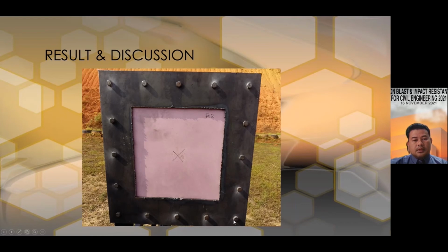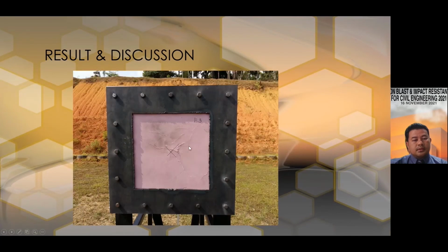Now, from observation, the gypsum board in case 2 does not have any damage at all. When there is no gap between the board and the steel plate, the board is good in resisting the compression force, but not the tension. The tension is provided by the steel structure. Compared to case 3, the gypsum board was heavily damaged. You can see clearly cracks at the middle of the board, and the cracks can reduce the fire performance of the gypsum board. However, it gives the best protection or absorption capacity and can protect the steel plate from deflecting.